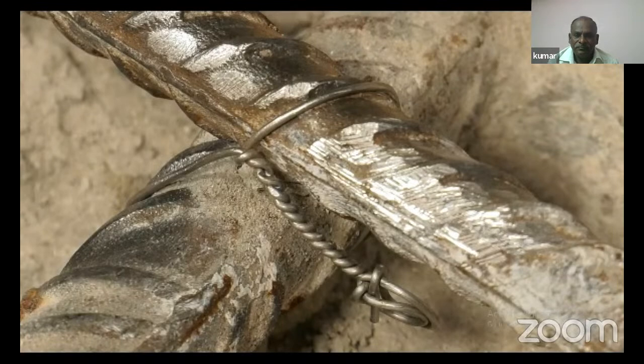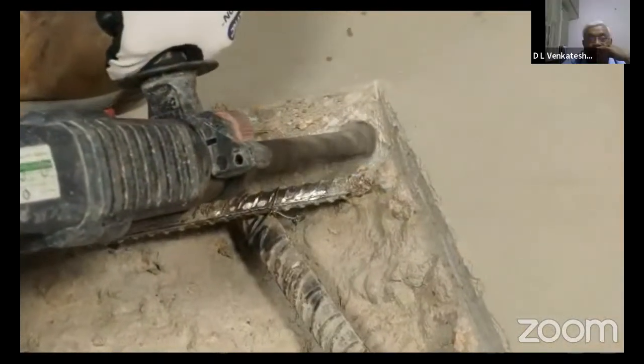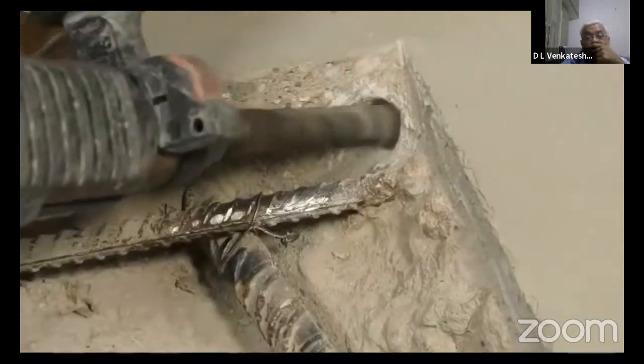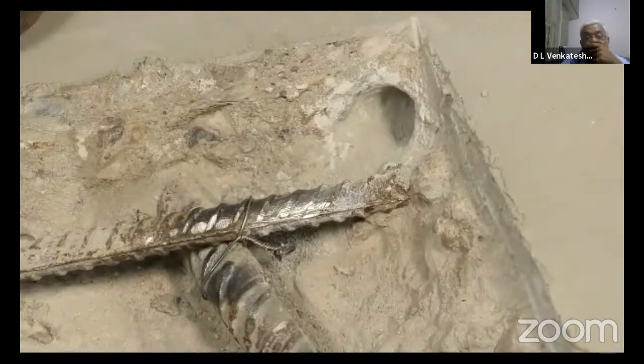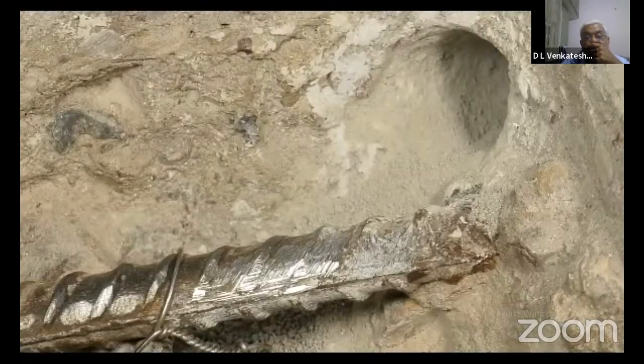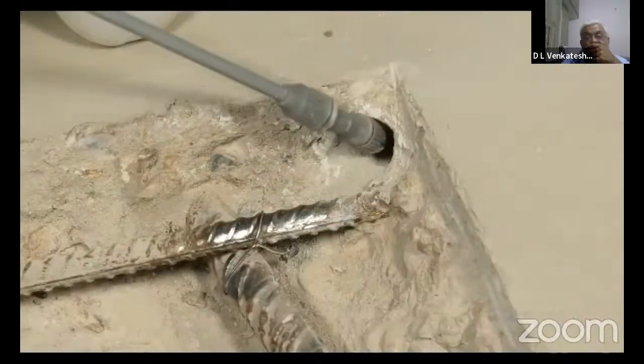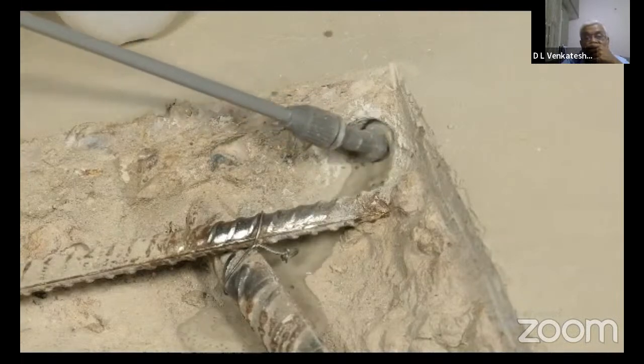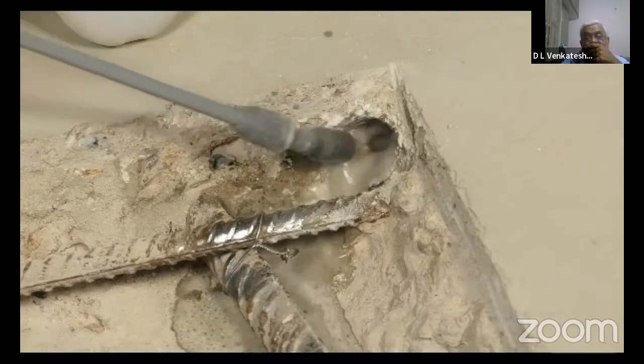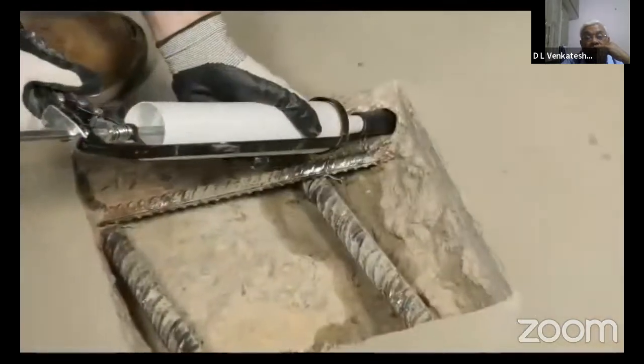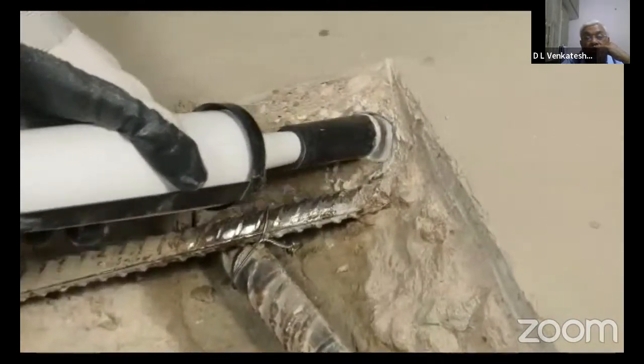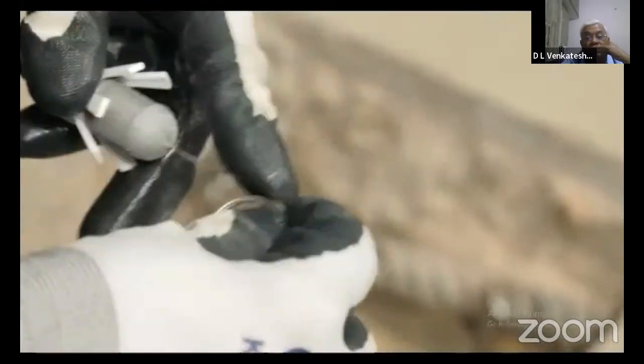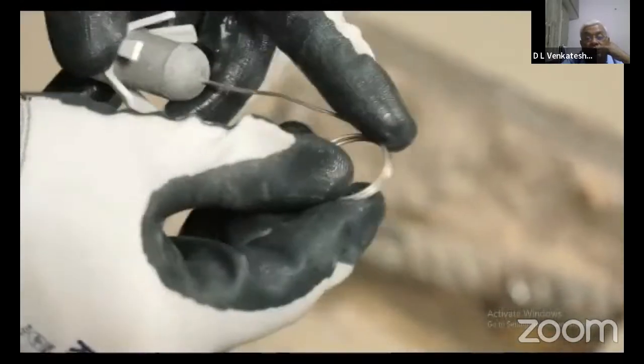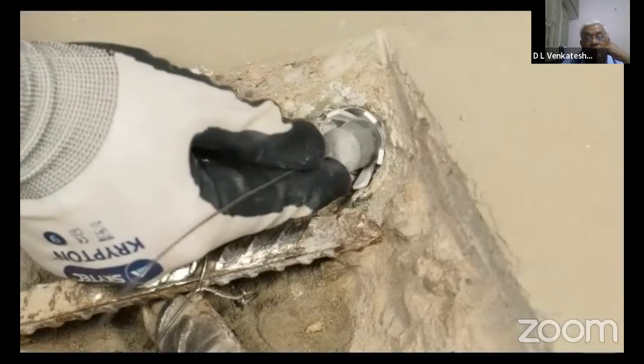required electrical continuity. Drill 25mm diameter holes to the depth required into the parent concrete at the side of the patch. Make sure to avoid contact with the steel. Next, soak the holes, making sure any excess water and dust is removed. Apply Duocrete PG mortar to the holes and insert the patch guard unit, ensuring that the whole anode surface is covered and that there are no air voids.